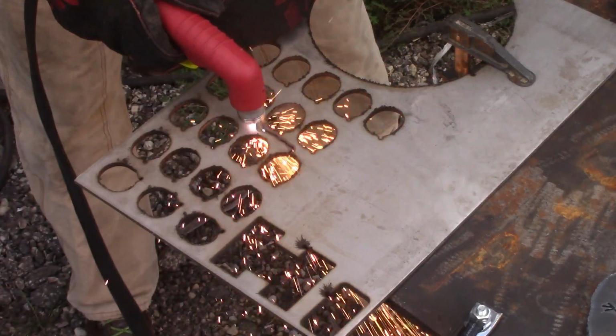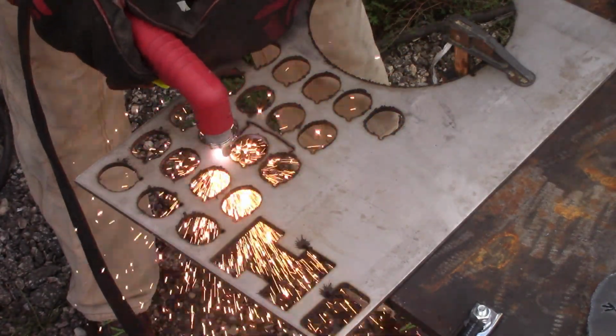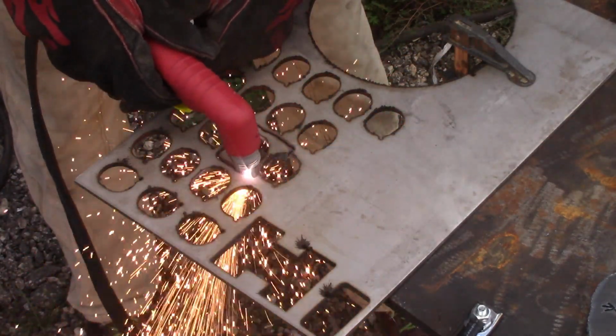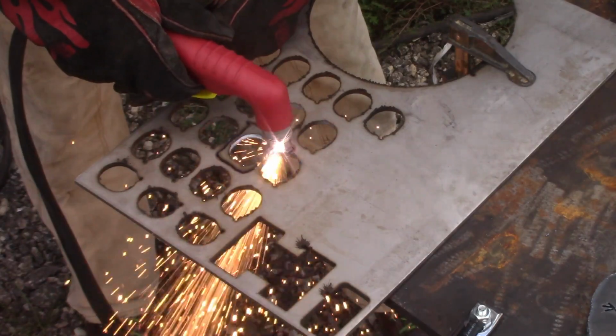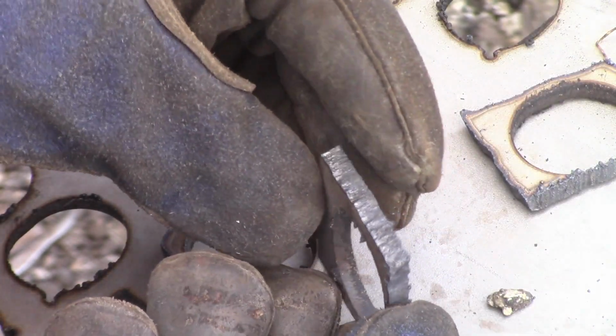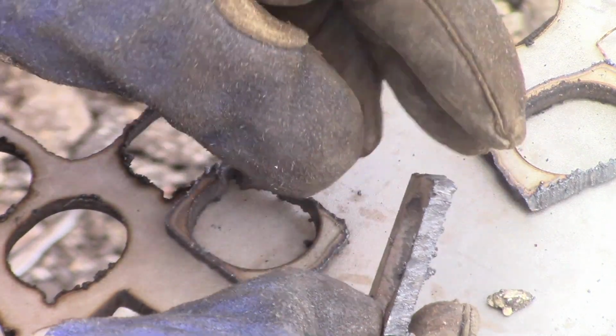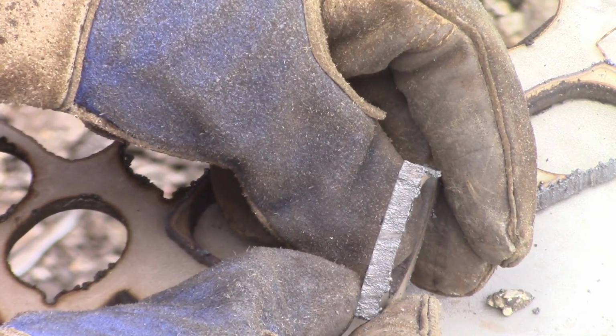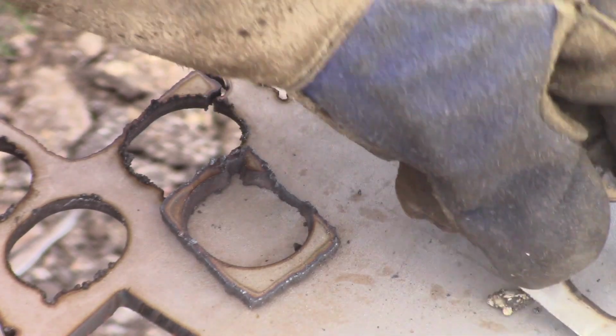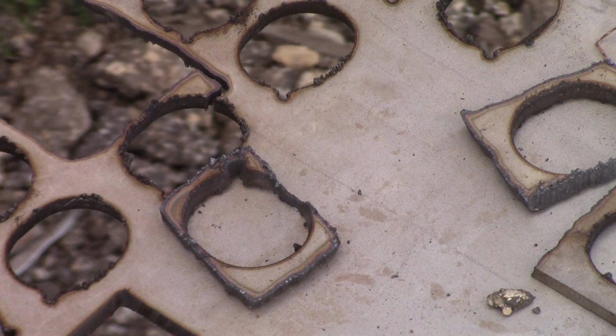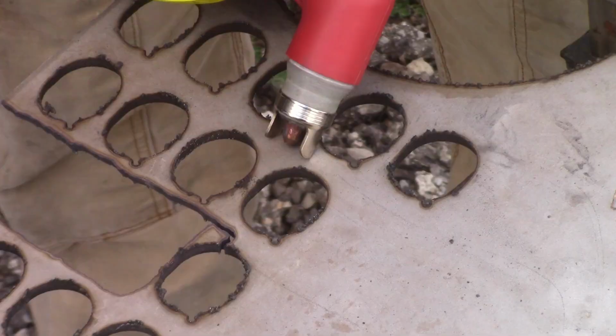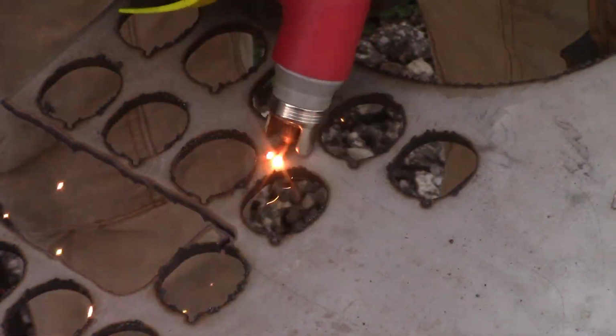We started with this piece of 1/4" stainless at 45 amps and 50 psi, and it went through with no problems at all. Cuts on stainless aren't super clean when cutting with shop air. They tend to look burnt and are quite rough. The dross also does not chip off like it does with mild steel, so you need to spend some quality time with a grinder. This is just a property of the material though.